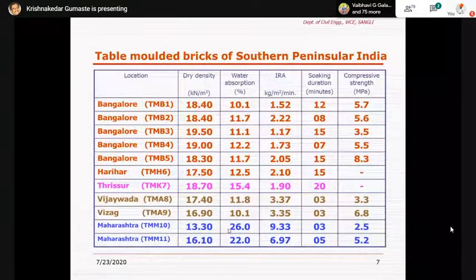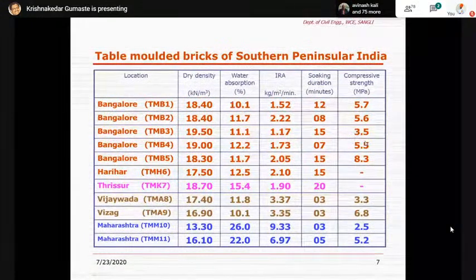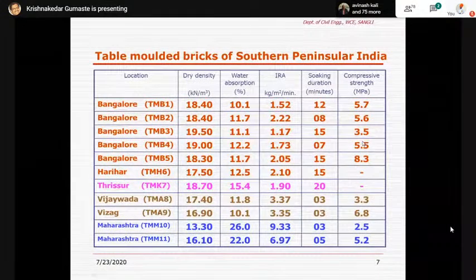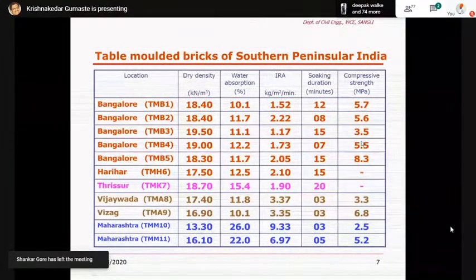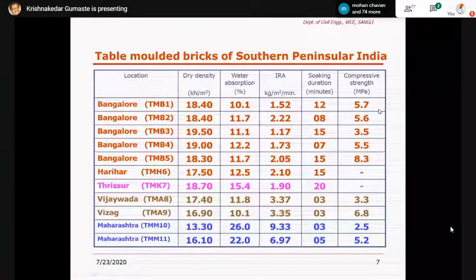So that is the kind of water absorption, and the density of the bricks also are in the range of about 13.3 kilonewton per cubic meter to a maximum of about 19.5 kilonewton per cubic meter. Although we cannot draw a judgment that higher the density, higher is the compressive strength, because you can see that somewhere where the densities are high, the compressive strength can be low. This is basically because of the other characteristics of how the material is vitrified during high temperatures, what is the temperature of burning, etc., which have a control over how the strength of the brick is being achieved.